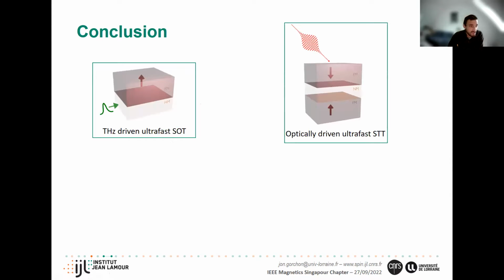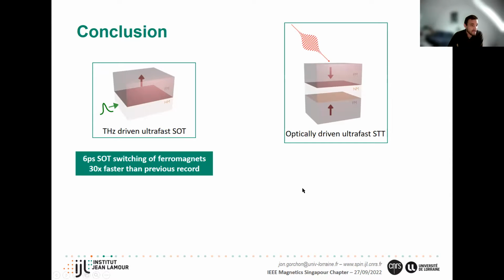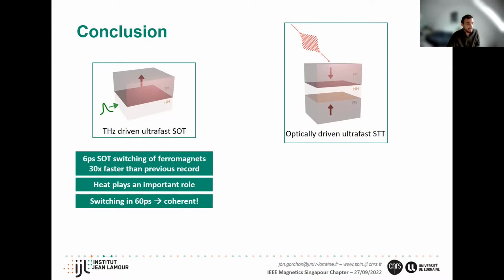So I'll finish with the conclusions. I've shown you that we can have spin-orbit torque switching with 6 picosecond pulses in ferromagnets, which is about 30 to 50 times faster than previous experiments. Heat plays an important role in this regime, and it can actually help. And we've observed that the switching can happen in around 60 picoseconds and seems to be purely coherent. Also, using direct absorption of femtosecond lasers to induce spin currents, we can get sub-picosecond switching of ferromagnets.